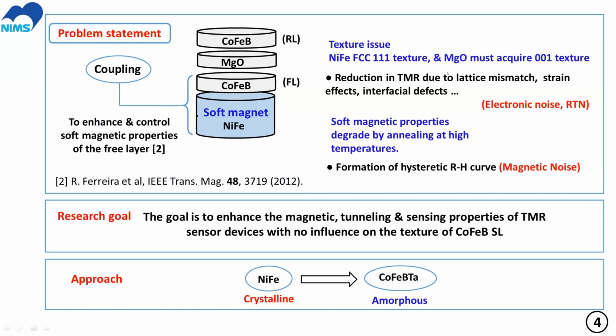Because of that, this lattice mismatch at the interface produces a strain effect or interfacial effect. It works as electronic noise at the interface. This is the reason why the TMR ratio decreases. Another point: when you anneal your layer structure at high temperature, like 300 or 350 for crystallization, the soft magnetic properties of the nickel iron start to degrade. Because of this degradation, it appears like hysteresis. And once hysteresis appears, the noise increases, and you can't use the MTJ as a good sensor.